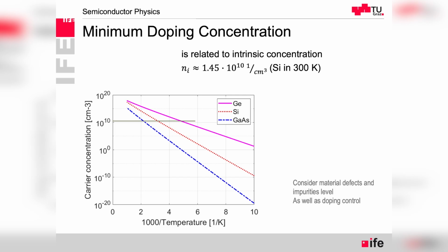jump ahead and talk a little bit about the history, just one mention. For a very long time, people thought that silicon is a metal because it was not possible to purify it early in the technology of silicon, so that we could see that it's a semiconductor and there is this temperature dependence of the charge carrier concentration. But there were so many impurities that it just looked like a relatively good conductor.